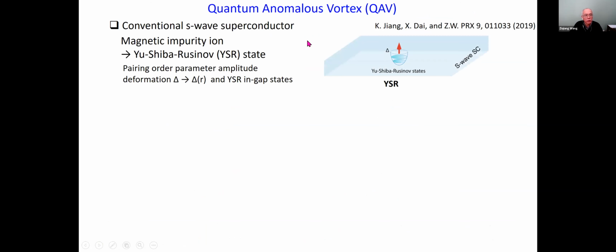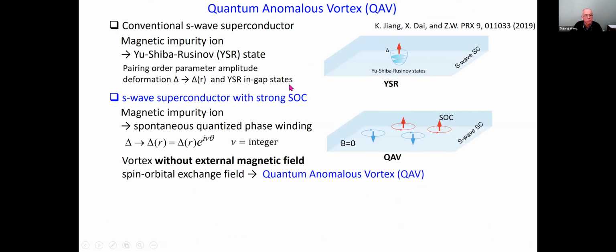So what is a quantum anomalous vortex? If we put a magnetic impurity in a superconductor, the breaking of time reversal symmetry will cause the Yu-Shiba-Rusinov states to appear. However, these are not vortices, and to have a vortex in a type 2 superconductor, you need an external magnetic field. So what we found is this conventional folklore changes in a fundamental way in an S-wave superconductor, let's say with strong spin-orbit coupling. In that case, if you put a magnetic impurity in the superconductor, a spontaneous quantized phase winding develops in the superconducting order parameter, and therefore a spontaneous vortex, if you wish, of the supercurrent without applying external magnetic field.